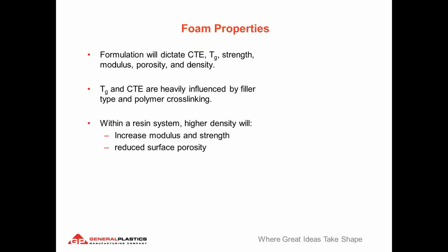Now, foam properties. They're very formulation dependent. Urethane foams are. Epoxy foams and hybrids thereof. Formulations really dictate what the coefficient of thermal expansion, that's the CTE, the glass transition temperature, strength and modulus, porosity, and of course density. And the glass transition temperature and CTE are two properties of the foam that really affect the engineers designing with the foam.